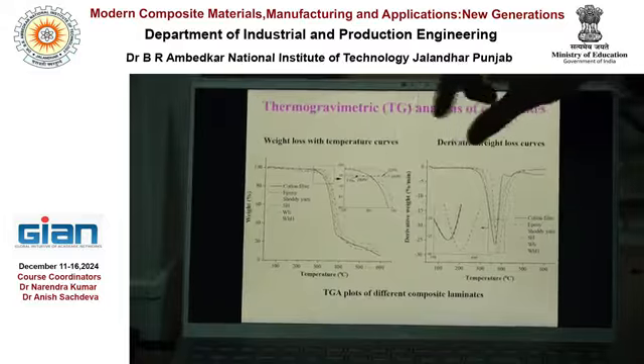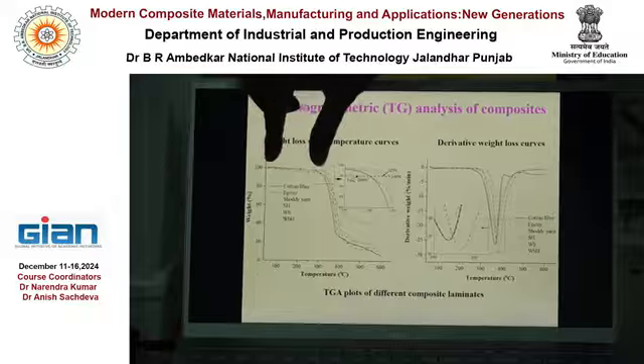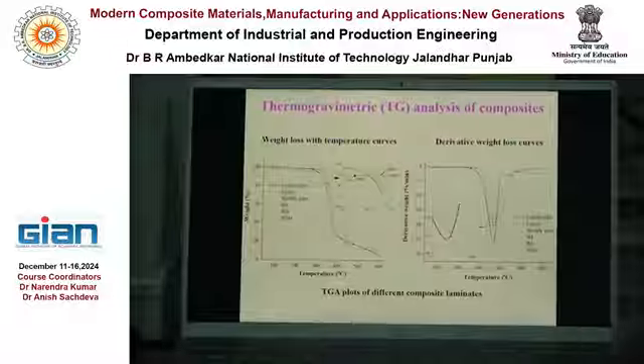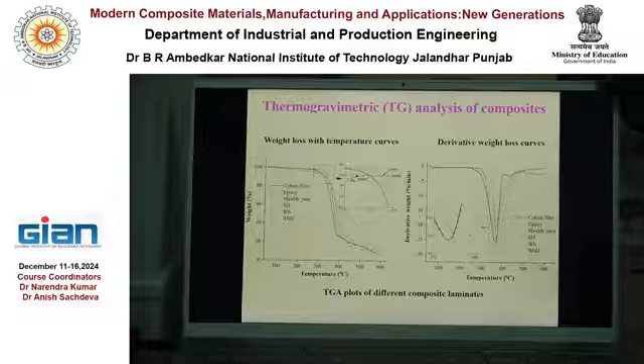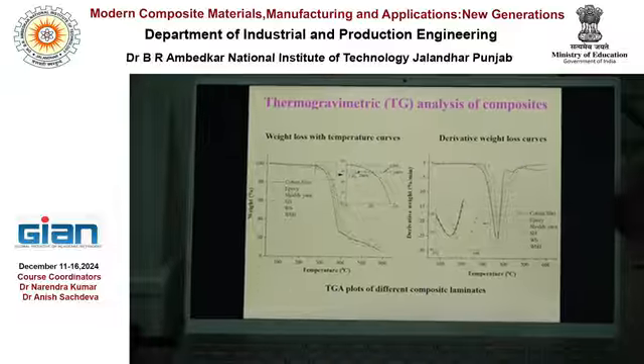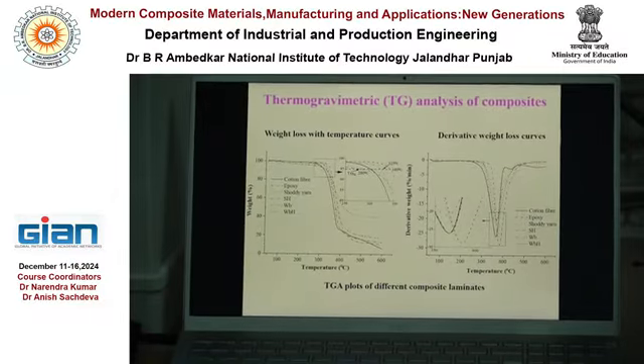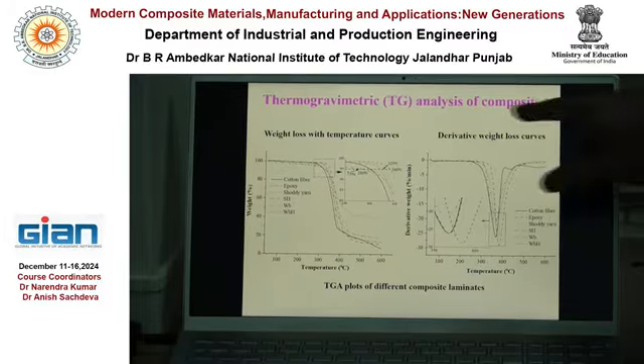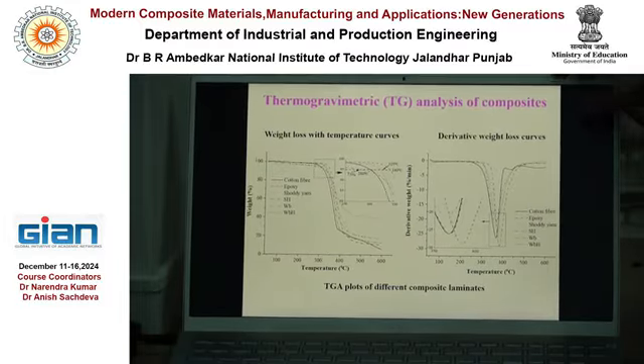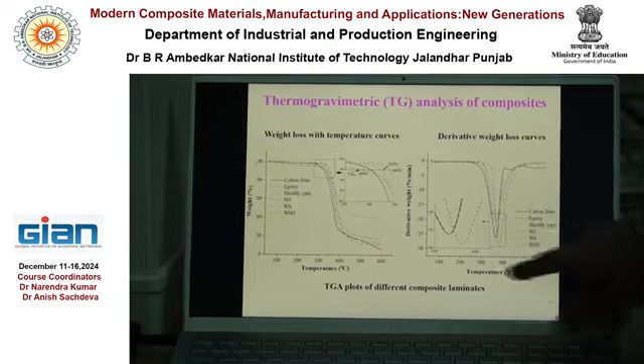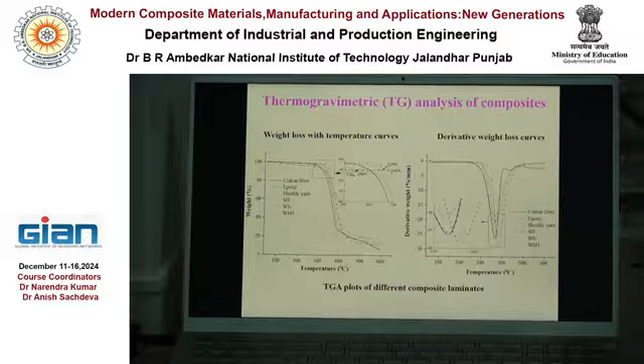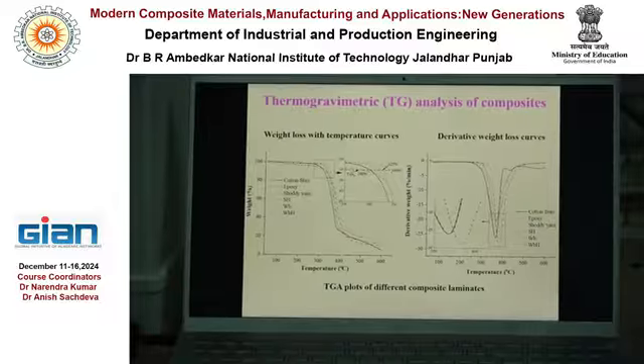So you can say that these cotton epoxy composites are thermally stable up to 300 degrees centigrade. You can see that there is a very, very small change in the weight of the composite material up to 300 degrees centigrade, and they are thermally stable enough up to that. If you look at this derivative weight loss, in this plot you will get temperature on the x-axis, and on the y-axis the percentage change in the weight per unit time.